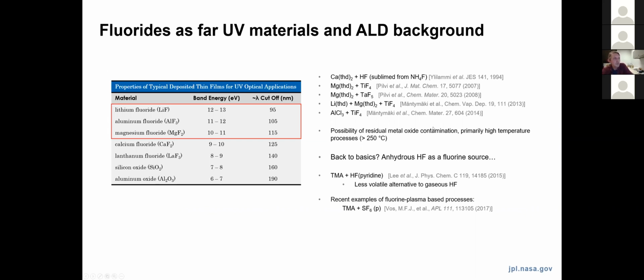There was previous work in the literature on ALD processes for metal fluorides, but they tended to be relatively complex from a precursor point of view. The metal organic compounds used in the processing were fairly complex, and in particular, the fluoride reactants used tended to leave residual metal contamination and required relatively high temperature processing. So somewhat incompatible with high performance optical coating. We decided at JPL to try to simplify this whole reaction pathway and use the simplest fluorine source that we could think of, hydrogen fluoride.